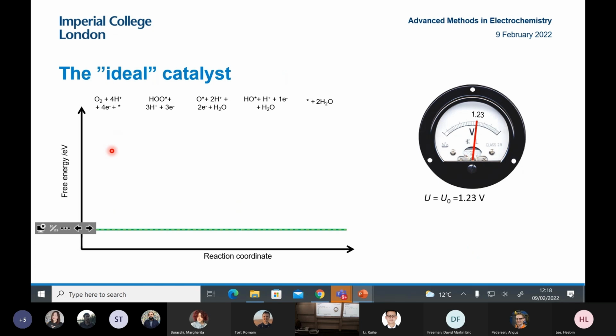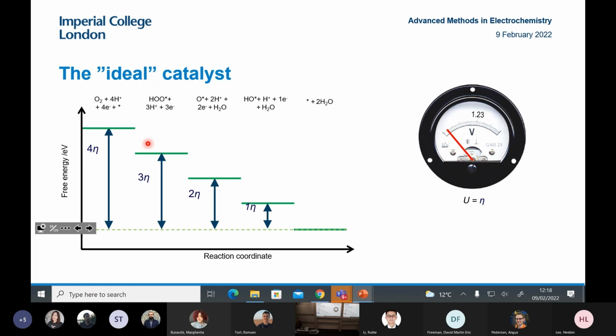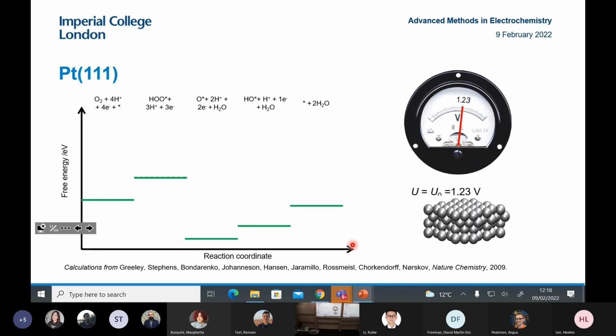So on the ideal catalyst, you'd have a completely flat free energy profile going from the initial reactants to final products. Then if you apply even a tiny overpotential, the whole reaction would be downhill, so you should be able to get large currents. However, it turns out that even on one of the best catalysts, which is platinum 111, which I already showed you the experimental polarization curve for, it's far from flat at the equilibrium potential. It's actually a bit corrugated.